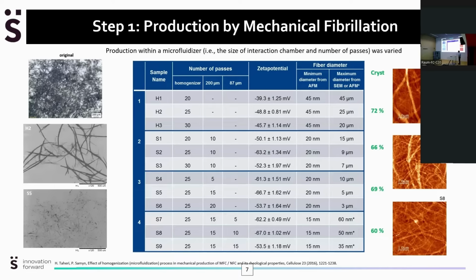It's a measure for the interaction of the fibrils. And what you see, indeed, is that with increasing fibrillation, you have a decrease in zeta potential. But if the fibrillation becomes too high, of course, you again have agglomeration of the fibrils, which is reflected here also in an increase in the zeta potential.